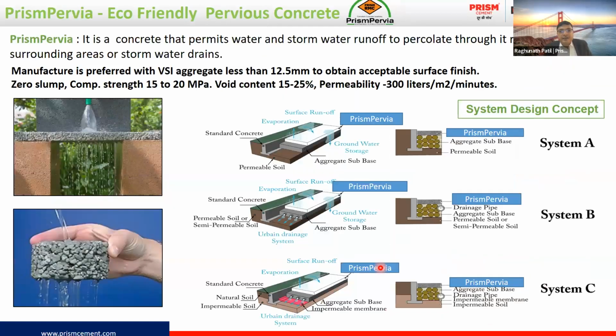Next, we have Prism Pervia. Prism Pervia is an eco-friendly pervious concrete. In this pervious concrete we do not use any fine aggregate. We manufacture this concrete only using coarse aggregates. One type of coarse aggregate only, 12.5 mm VSI aggregates, is used in this application. This concrete generally permits water to percolate from the ground to the underground soil, so rainwater or stormwater can